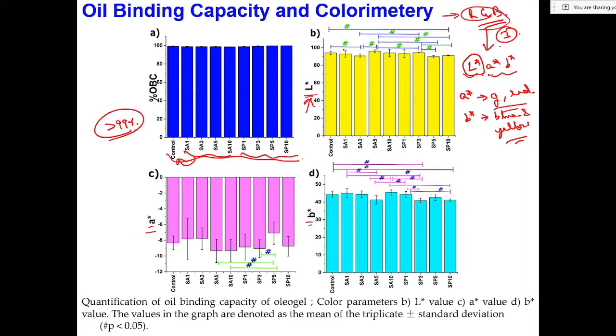So if you see these hash signs, they show that, suppose in control and SA3 we are showing this hash line, that means there is a significant difference between the L star values of the control and the SA3, and the significance level we have taken is 0.05. Okay. So if you see clearly over here in SA3 as compared to the control, there was a decrease and then again there was an increase in the L star value. Okay. So this decrease in SA3 was significantly lower as compared to the control.